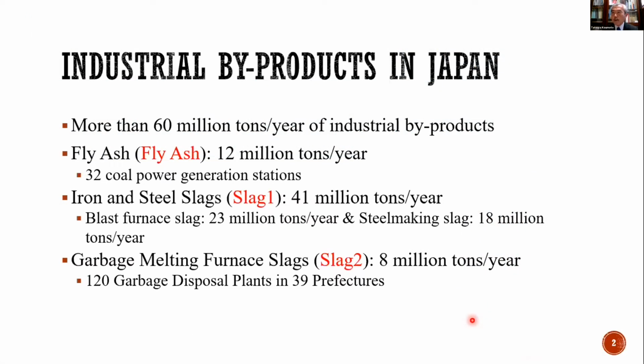Production is more than 60 million tons per year, including fly ash of 12 million tons per year from 32 coal power generation stations, and the iron and steel slags, that is slag 1, of 41 million tons per year, including blast furnace slag of 23 million tons per year, and the steelmaking slag of 18 million tons per year. And garbage melting furnace slags, that is slag 2, of 8 million tons per year from 120 garbage disposal plants in 39 prefectures.